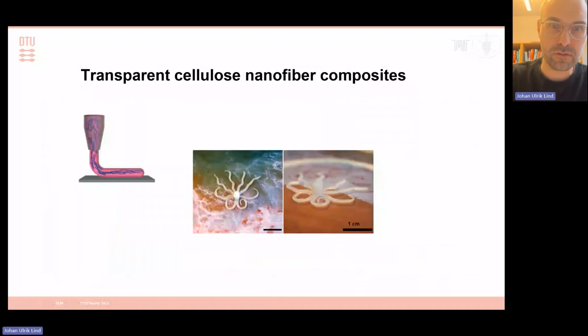So then we turned to what I showed in the beginning, whether we can use anisotropy within the print material as a guiding principle. So cellulose nanofibers have been studied a lot, obviously, as an additive for extrusion-based printing and extrusion-based bioprinting, and most formulations are non-transparent. So if you get microfibrillated cellulose, your prints will look white. And that's a problem if you do a lot of microscopy like we do, as we would like to be able to visually assess the cells easily.